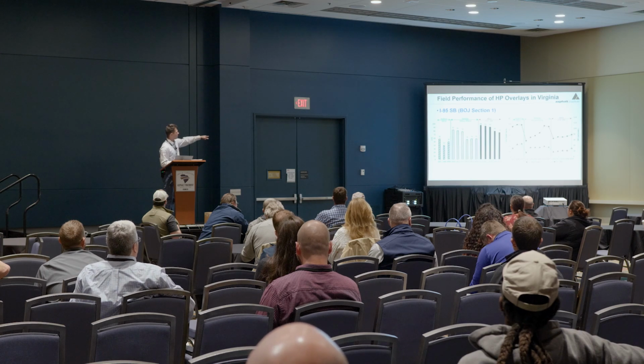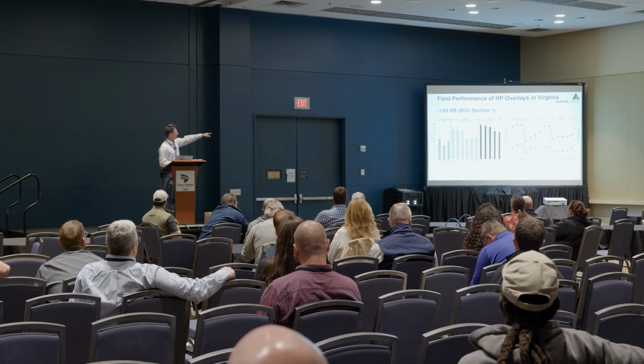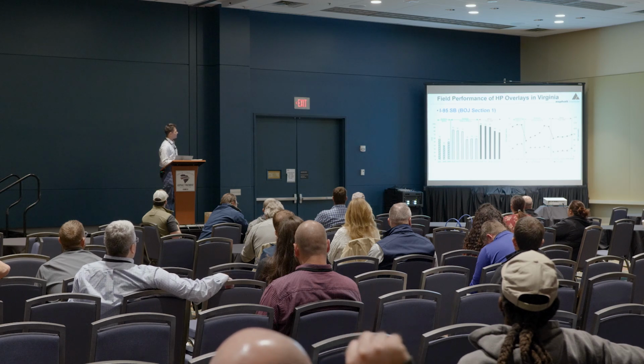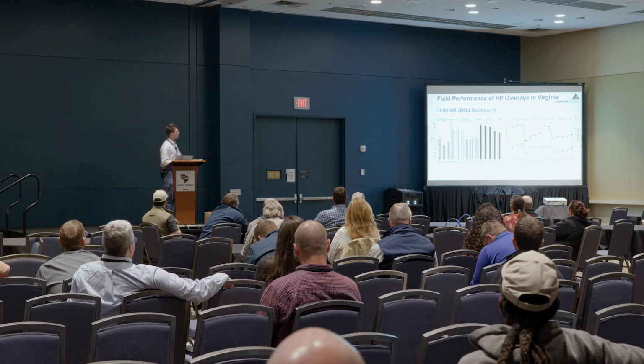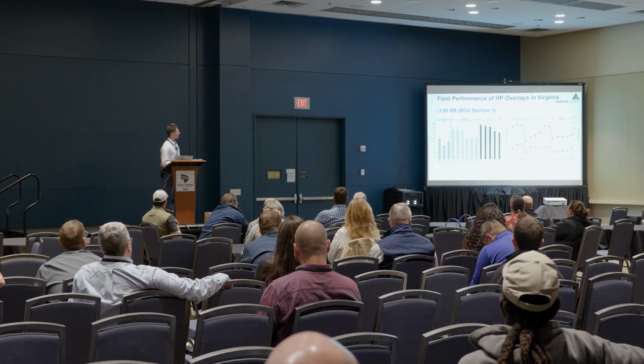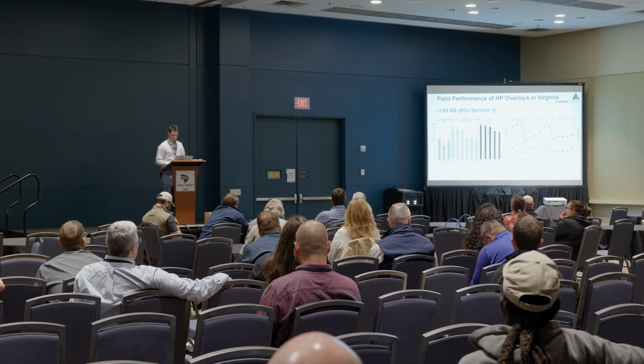rehabilitation. So you had the initial, and then you had the SMA was built in 2010. And then they went with a high polymer dense mix in 2016. So really what you're looking at there is just the rate of deterioration. And just by observation, you can see that the high polymer mixture is really resisting deterioration a lot better, even than the SMA, which is itself a very durable and strong mixture. And on the rut depth, it's kind of the same thing.